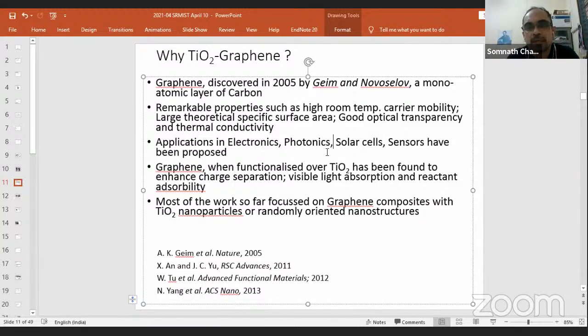So when graphene was discovered in 2004-2005, immediately in 2008, at that time I was still doing my postdoc at Penn State, a paper came which showed that in a TiO2 graphene composite, if you have graphene layers intimately wrapping TiO2, the graphene can take out electrons very quickly.